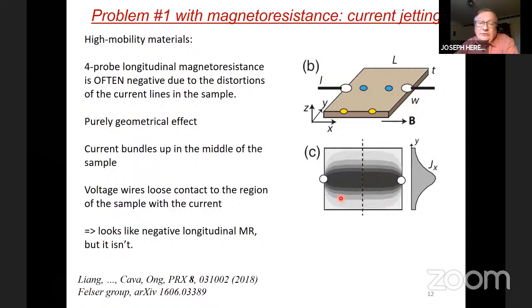Well, that means that the Lorentz force has a strong grip on these carriers. And if you have a situation where your current injecting electrodes on your sample are here and here, well, of course, in low magnetic fields, the current distributes itself through the sample, but you apply a magnetic field parallel to the current, that does tend to concentrate the electrons on a helical path in the middle of the sample. So the current distribution stops being uniform through the cross-section of the sample, it concentrates in the middle. And if you have voltage electrodes here, the voltage electrodes are placed at a location where there is no current. So the voltage goes very small, and that to you would look like a negative magnetoresistance.